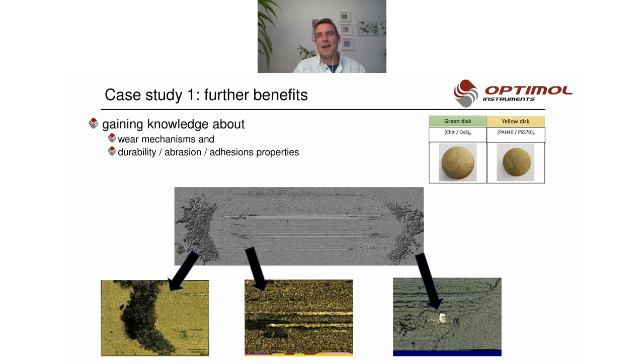Besides that, there were two of those which are not suitable for those applications: the already shown yellow one, as well as the green coating here. And you are able to gain more and more knowledge besides those data of friction and wear, because you are able to set up your loads and your speeds, and you will end up with different kinds of wear mechanisms, and you are able to have a deep look and a good understanding of what's happening there and why the systems are failing. For example, adhesive wear, so spalling of the coating, scratches, or the production of wear debris, and you don't want to have them in your eyeball.